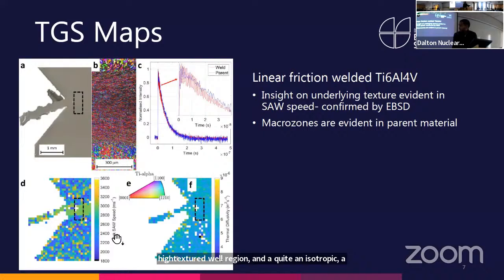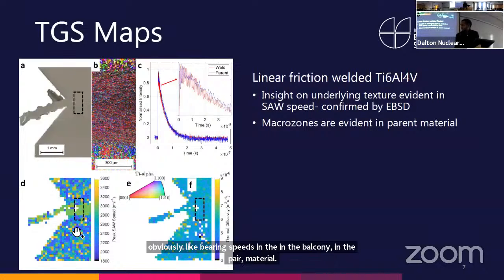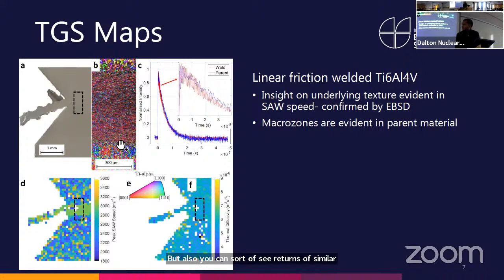And looking at the surface acoustic wave speed map, you can also see a uniform surface acoustic wave speed in the weld, and then obviously varying speeds in the bulk, or say in the parent material. But you can also see regions of similar wave speeds that coincide with these macro zones in your parent. And the thermal diffusion map is pretty even throughout. And yeah. So let me move on.